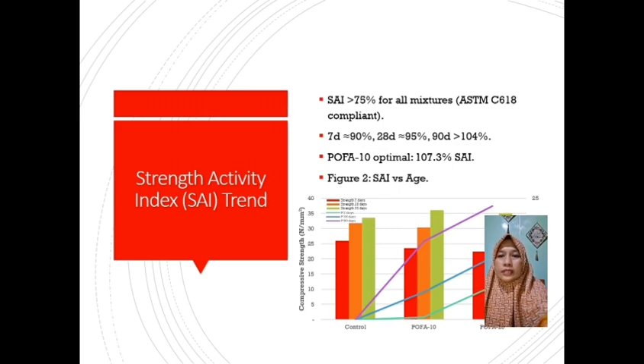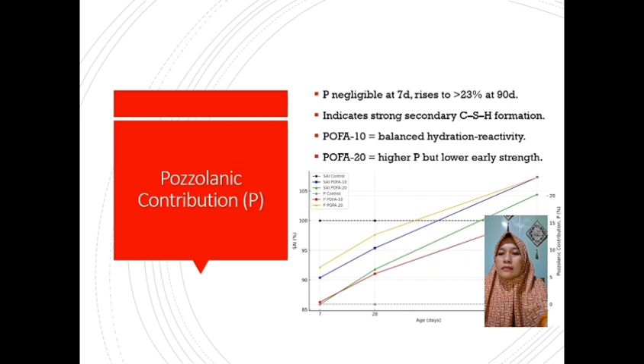The pozzolanic contribution quantifies the portion of total strength derived from pozzolanic reaction. At 7 days, values were negligible, reflecting cement hydration dominance. At 28 days, the pozzolanic contribution increased to above 5 to 13%, and at 90 days, it reached 19 to 23%, particularly in 20% POFA.